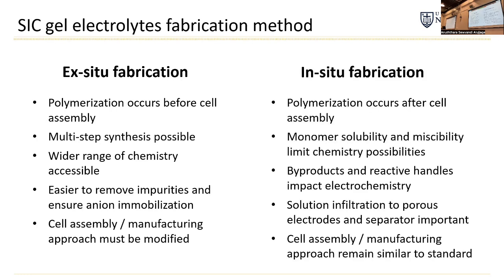And so we were approached by a company who's been pursuing in situ fabrication. With this method, which others have worked on as well, and there's some literature, polymerization occurs inside the battery cells. So you can imagine that you infiltrate the monomers that form the polymer into the cell, and then you cure it and form the polymer afterwards. The downside of this is that the monomer solubility and the miscibility with the things in your electrolyte limits the type of materials you're able to make, right?